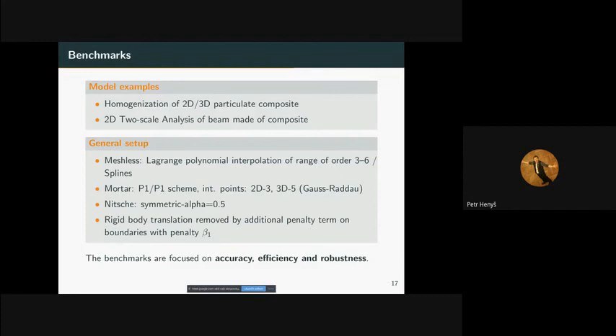And from that idea, you can remove the mean value from your model by simply adding an additional term in your weak PDE. For example, you can say, okay, let's constrain that the mean value should be 0, right? Which tells you that the translation is not allowed anymore. This actually means that you will add an additional term, which is quite similar to periodicity, but it is just an integral over the whole domain of the displacement field, right? And you will just say, okay, this I want to be 0, right? Then you can force it by the penalty, or you can force it even by a Nitsche or mortar method, doesn't matter what you choose.